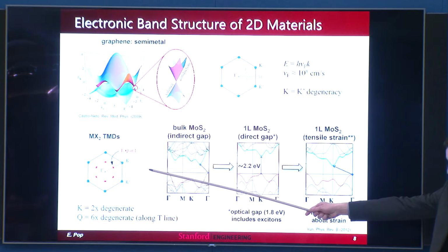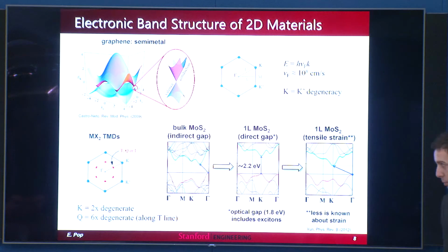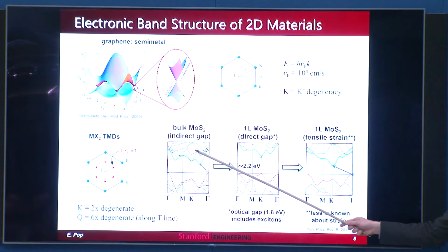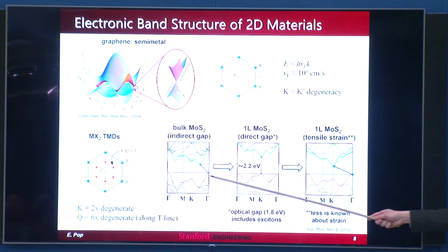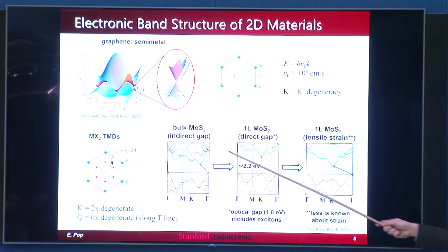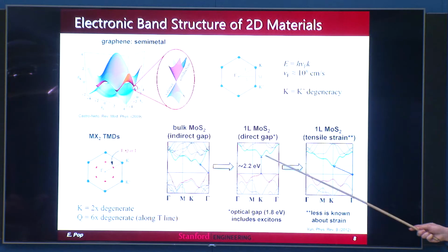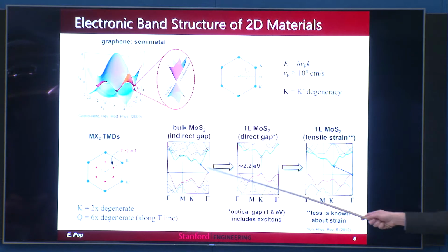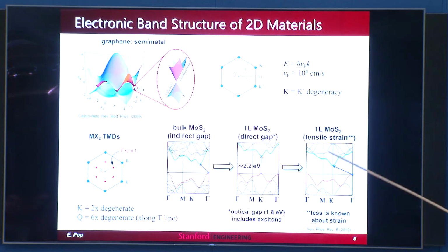The 2D materials which are semiconducting have also a hexagonal Brillouin zone, and they have some funny band structure, which sometimes I think is not necessarily pointed out, but I really wanted to point it out here. In bulk, they tend to be indirect band gap. In monolayer, they tend to be direct band gap. And you can see that these conduction band valleys are actually dancing around, depending if you go to bulk, monolayer, or if you apply tensile strain for that matter. You can actually break the symmetry again, change the valleys around, increase mobilities, change the valley separations, and so on.